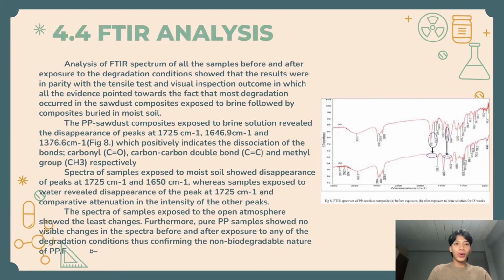Spectra of the sample exposed to moist soil show disappearance of peaks at 1725 cm^-1 and 1650 cm^-1, whereas the sample exposed to water revealed disappearance of the peak at 1725 cm^-1 and comparative attenuation in the intensity of the other peaks. The spectra of the sample exposed to the open atmosphere showed less change. Furthermore, pure PP samples show no visible change in the spectra before and after exposure to any of the degradation conditions, thus confirming the non-biodegradable nature of PP.